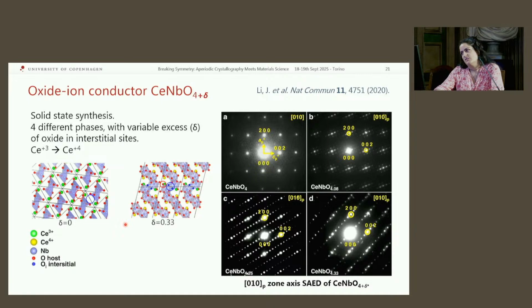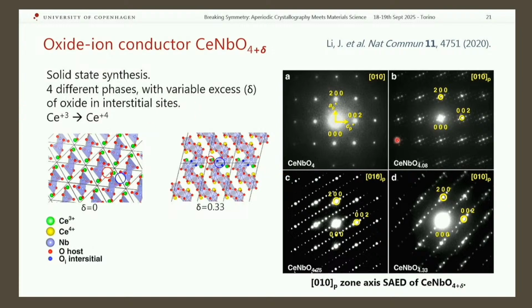I have another example, which is not something I personally analyzed, but it's extremely cool, because it's showing you how the modulation is also explaining the function of the material. So this is an oxide ion conductor, which could be a battery material, for example. Here, it's again cerium niobate with excess oxide, and they synthesized 4 different phases with a different amount of excess oxide, and this is compensated by the easy oxidation of cerium 3+ to cerium 4+. So if we look at the extreme structures, the stoichiometric one without excess oxide and the one which is the most oxygen-rich, we can see that in the second one we have extra oxygen, which is occupying some interstitial sites, and it's here in blue. And both structures are actually ordered.